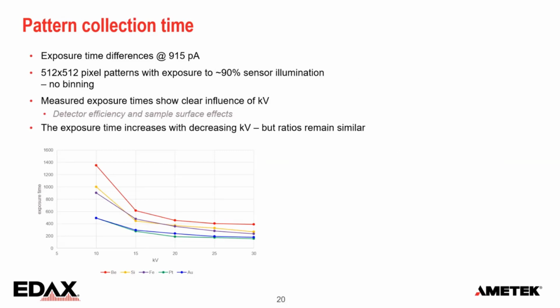And if we then try to collect data on these samples, this is the data from the plot on the previous slide. You can see the exposure time required with accelerating voltage. This is at 915 picoamp, and we just keep counting until we have about 90% sensor illumination. So, more than 10,000 electrons per pixel on average. What you'll see here is that from 30 to 20 kV, there's not much difference. To 15, it starts to rise a little bit, and at 10, it really goes up.